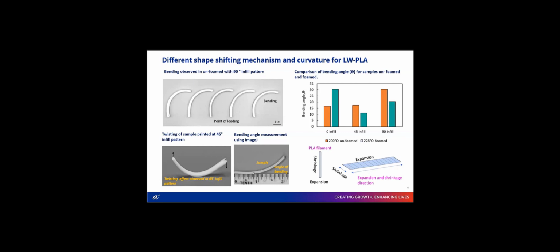Also, the bending angle differs for each process parameter combination. For each extrusion temperature and combination of infill pattern, we obtain a different bending angle, as plotted in the graph. From this, we can say that the infill pattern and the extrusion temperature affect the bending angle, and the recovery time and the bending angle. The bending angle is different for the 0-degree infill pattern and different for 45 and 90.